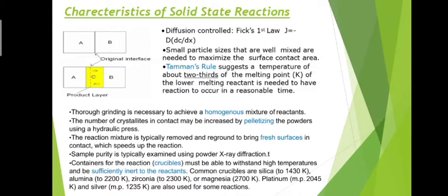The number of crystallites in contact may be increased by pelletizing the powders using a hydraulic press. The reaction mixture is typically removed and reground to bring fresh surfaces in contact, which speeds up the reaction.